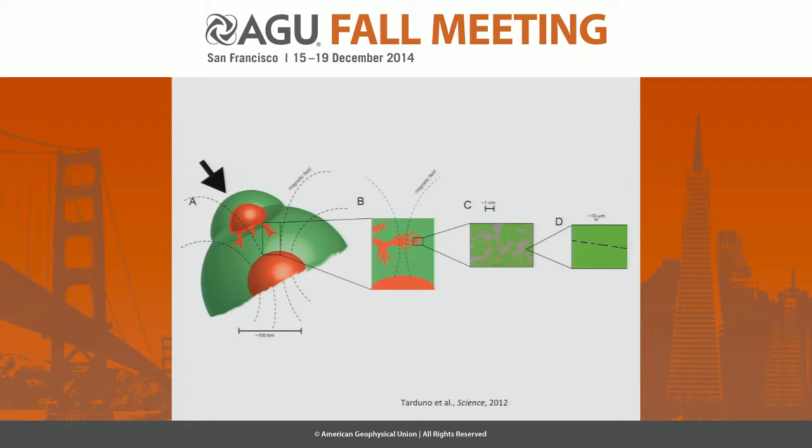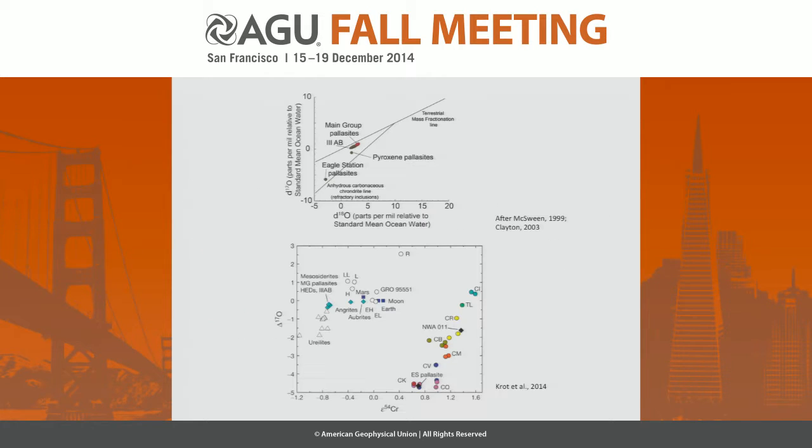And this is hit by an impactor that is differentiated as well. So we can see that here. And then we have the metal from the impactor mixing with the silicate mantle through dikes of the metal from the impactor and the silicate mantle. And this gives the pallasites their characteristic metal-olivine texture. Small fractures in the olivines can open up and are injected with metal. This is what retains the magnetizations that we record in our olivines.